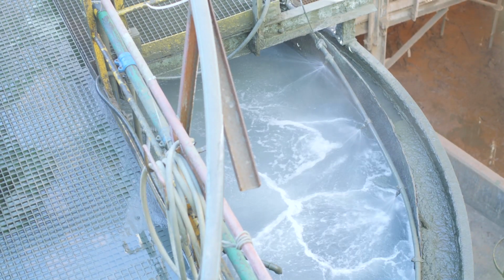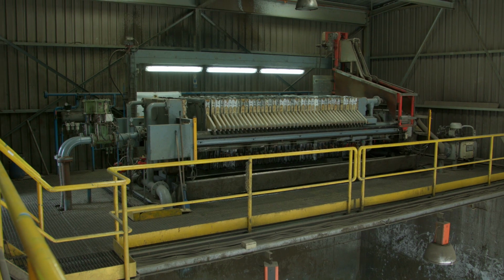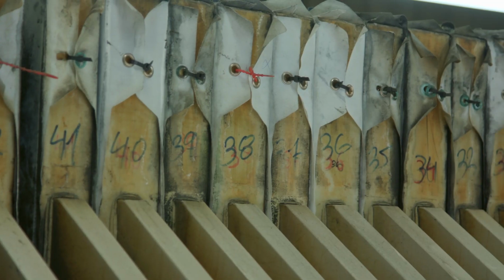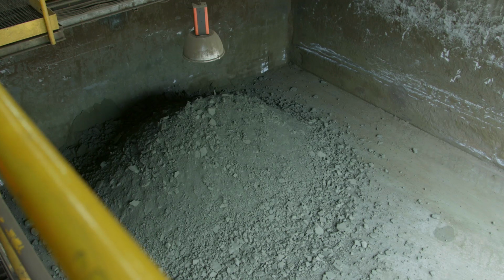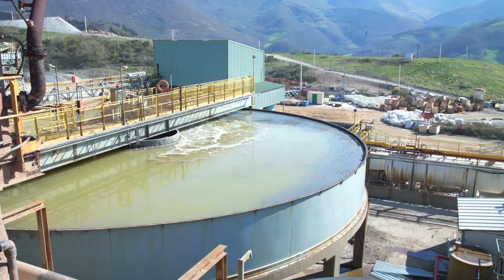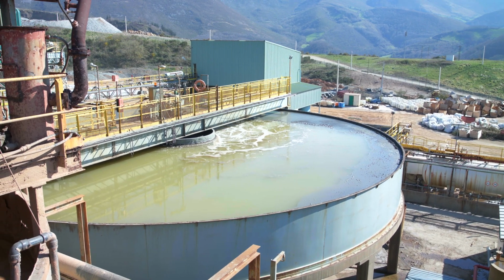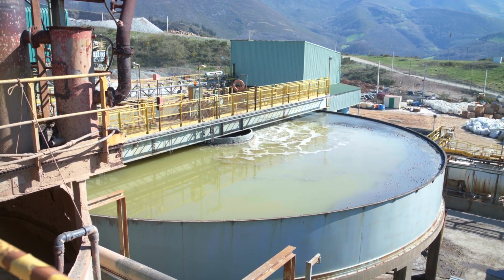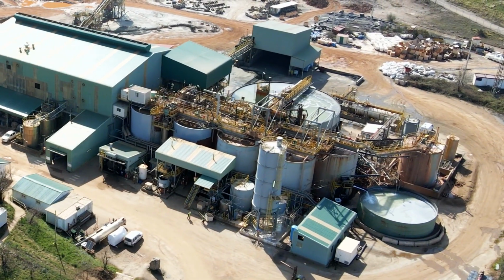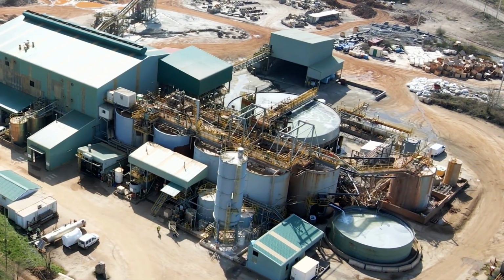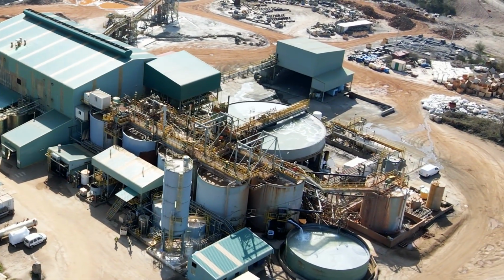The foam is subjected to a thickening and subsequent draining process with a filter press to lower the humidity to 10 to 12%. This is how we obtain the copper concentrate. The residual pulp from the flotation circuit, after passing through a thickener, is subjected to the SIL process of gold leaching and subsequent absorption into activated carbon.